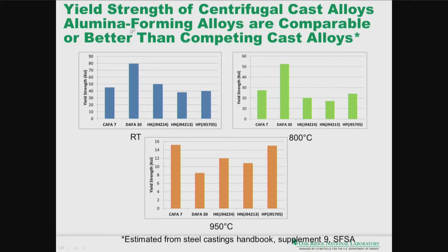So in terms of the strength, here's data showing the strength of these alloys at 3 different temperatures. As you can see, the DAFA 30 is aimed at being a very, very high strength alloy, and is at least about double the yield strength of the other austenitic stainless steels that we show here. CAFA 7 does well, and it's at least comparable, maybe slightly lower at room temperature than HK, but definitely better than the HN and the HP.